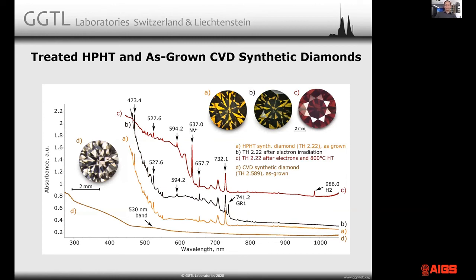It'll turn somewhat greenish brown. It's like an olive-brown color, pretty dark in this case. You can see what happens. Prior to irradiation, you have trace A. These are all nickel-related defects that you see here. The nickel-related defects are in part responsible for this overly dark yellow, brownish yellow appearing color.